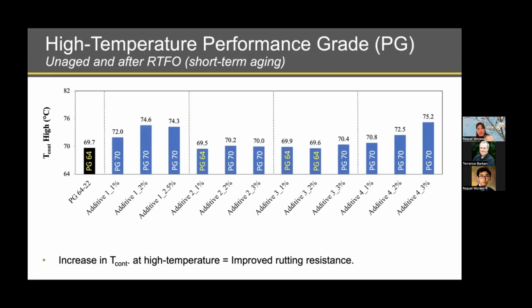So on this slide, I have the results of the high temperature performance grade of the base asphalt binder and the asphalt binder modified with the graphene additives. The number indicated on top of each column is what we call the pass-fail temperature. It's the maximum temperature that a specific asphalt binder could hold. Some of the binders presented a slightly lower pass-fail temperature than the base binder, but as we increased the dosage, that trend changed. We did not see a specific decrease in the high temperature of the binders after incorporation of the graphene. Overall, the trend was that after the graphene additives were incorporated into the base binder, we saw an improvement in rutting resistance in terms of high temperature performance.